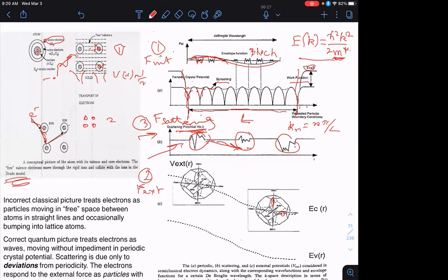While the periodic forces also have an impact on the electron, that impact is captured by this effective mass. So I'm not ignoring the periodic forces. It's just that I'm capturing that as an effective mass, and since it's perfectly periodic, those Bloch type wave functions can propagate forever without colliding with the periodic atoms themselves. All right. So once I have that effective mass, the only time I'll have collisions or scattering is from any deviations from periodicity.